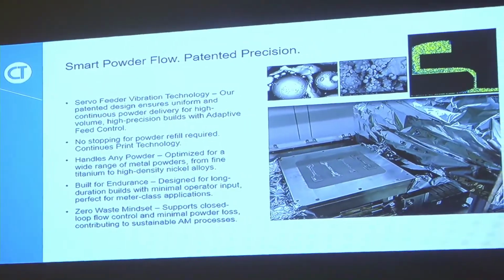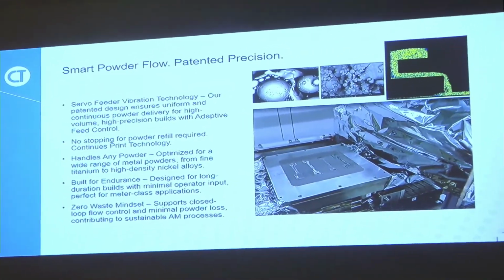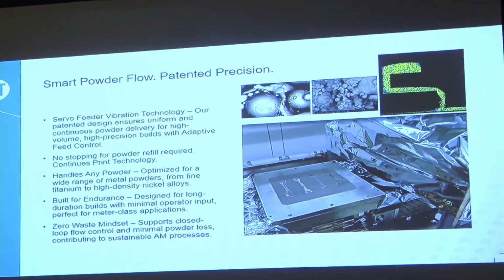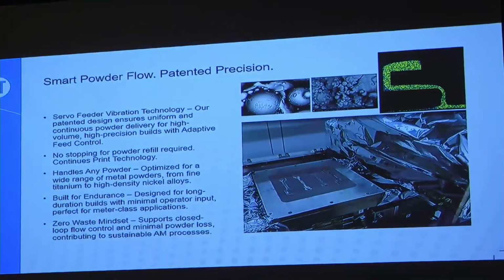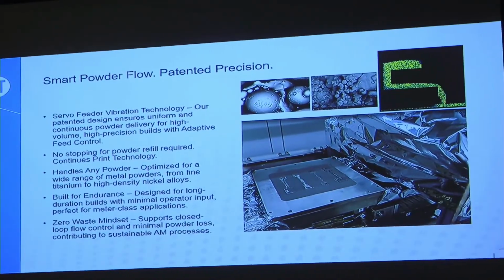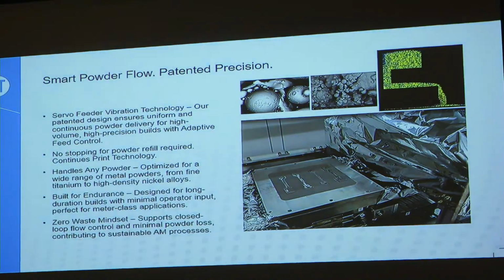So then we talk about powder feeding. Powder feeding for us means we can feed powders that a lot of people cannot use. We have a lot of good results with, for example, totally random formed water atomized powders. So these are very low cost, right? But they cannot be used because they don't flow. They have zero flowability, right? But because we use actually a vibration-based system, we can basically make them flow over the area and we just make them into a layer. Okay, that's part of this.